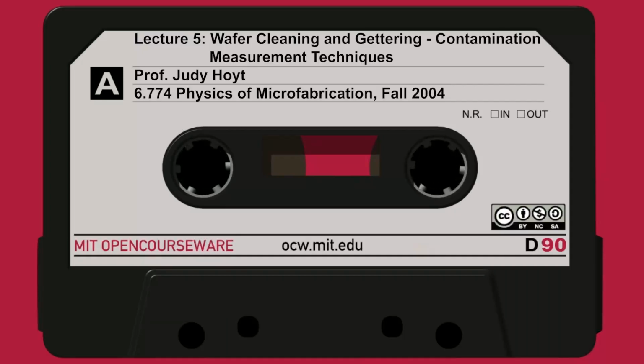That's okay, but if you wanted to look, let's say, inside an individual device and see what impurities were in a bad device, if you had a failed device, TXRF is not the way to go, because the devices are much smaller than 10 millimeters. That's the whole die on that wafer being passed around. And the surface has to be specular and polished.